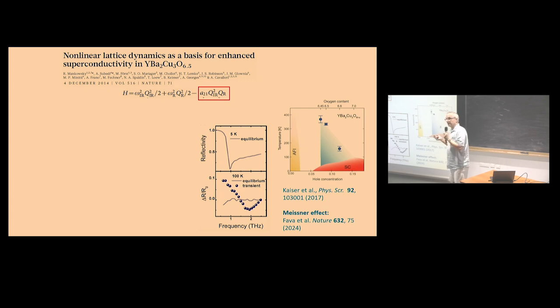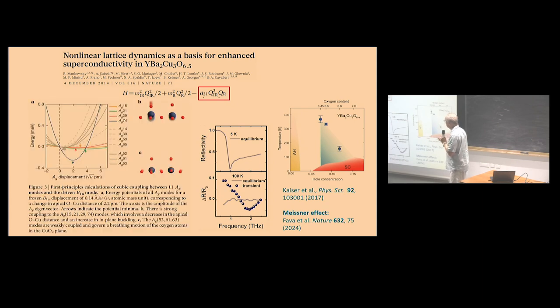some transient superconductivity here, in this concentration of free carriers. They observe it even slightly above room temperature. It is, of course, a transient effect. It is on a picosecond time scale. And what happens here, this is a calculation: coupling of a high frequency phonon, again this phonon around 20 terahertz, is coupled with Raman modes, and here it is taken into account that there are 10 Raman modes, and how efficient the coupling is for change of potential, and finally this blue one is the most efficient, and it can produce practically a shift of oxygens, and it goes closer to the CuO or copper oxide layers, and then you can enhance the superconductivity.